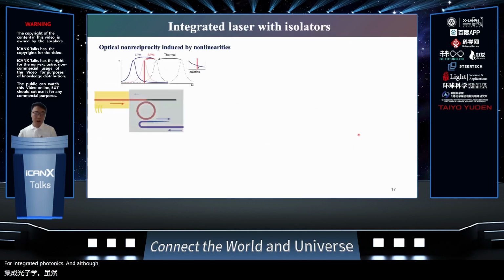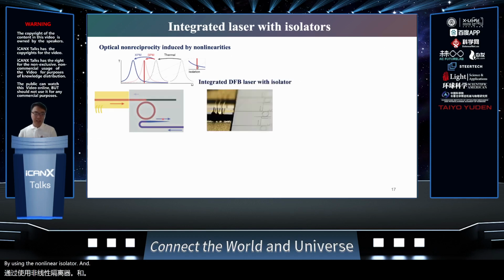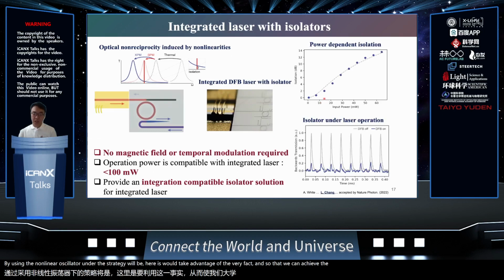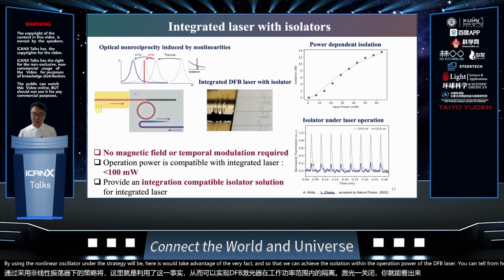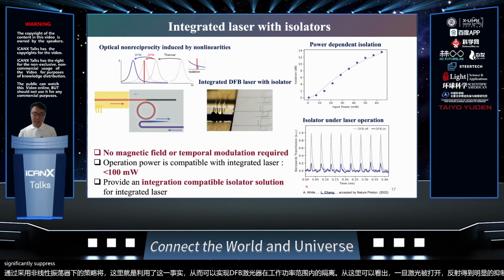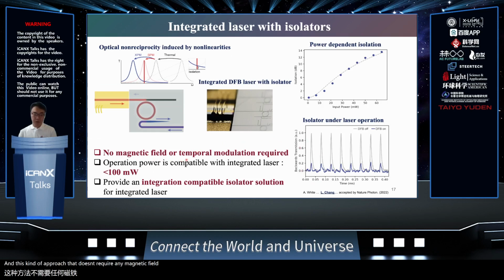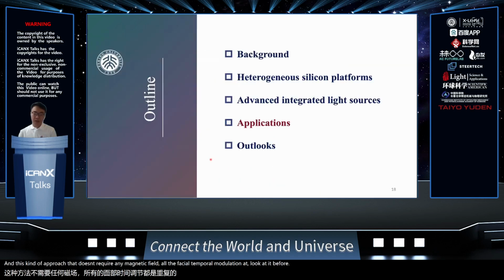Although all of the properties I mentioned before are very important for photonics, without isolators they couldn't be really useful. We also demonstrate the first integrated isolator together with lasers in integrated photonics by using a nonlinear isolator. The strategy we use here is to take advantage of the Kerr effect, so that we can achieve the isolation within the operation power of the DFB laser. You can tell from here, once the laser is turned on, the reflection gets significantly suppressed. This approach doesn't require any magnetic field or the spatial temporal modulation as required before. So with these advanced devices, we use them to extend the scope of silicon photonics for many new applications.